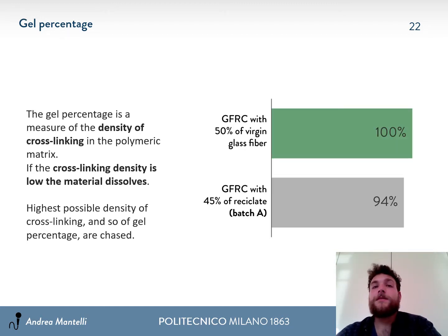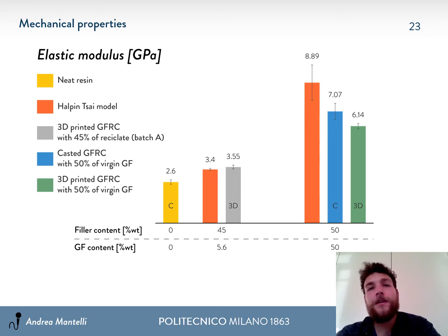As a benchmark, you can see the result of the material filled with virgin glass fiber, that is good, 100%, and even though the result for the recycled composite is good, more tests are needed to reach a higher gel content. Moving to the mechanical properties, here you can see the elastic modulus for the neat resin and for the composite materials. As you may notice, even with 45% of recyclate in the material, the glass fiber content is very poor, and the mechanical properties are quite similar to the neat resin. On the other hand, for virgin glass fibers, we have a very high benchmark. Anyway, considering the real content of glass fiber, the results are comparable with the Halpin-Tsai model prediction.